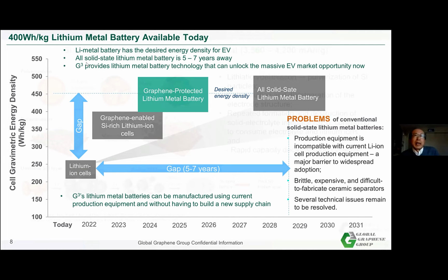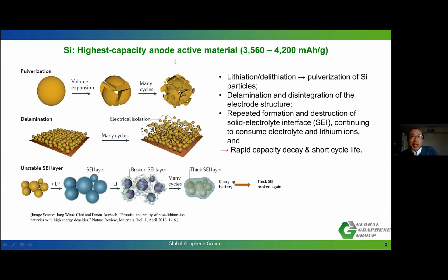And if you look at silicon, which is right now the hot topic in the lithium-ion battery industry, traditionally lithium-ion batteries make use of natural graphite or artificial graphite as the anode material. And the graphite itself has a limitation in the sense that the specific capacity of the graphite is typically between 340 and about 370 milliamp hour per gram. In contrast, silicon itself can store up to about 4,000 milliamp hour per gram. It's almost 10 times the specific capacity of the graphite. Well, this does not come without a problem.